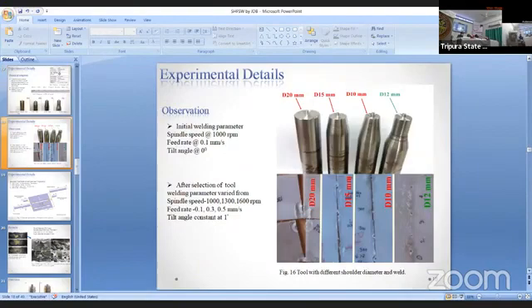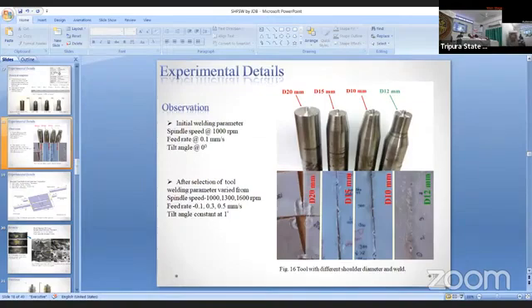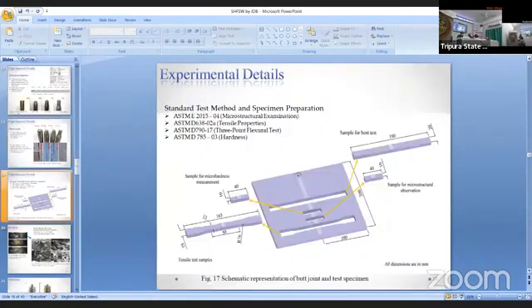Then it was observed that the initial welding parameters were set at 1000 RPM, feed rate at 0.1 mm per second, and tilt angle at 0 degree, because tilt angle also plays an important role, as I've already mentioned. And welding has been done. The weld quality was not very satisfactory, as we have observed in these cases. Of course, there are various reasons. I'm not going into more details.